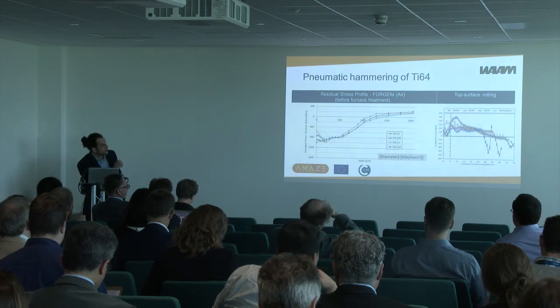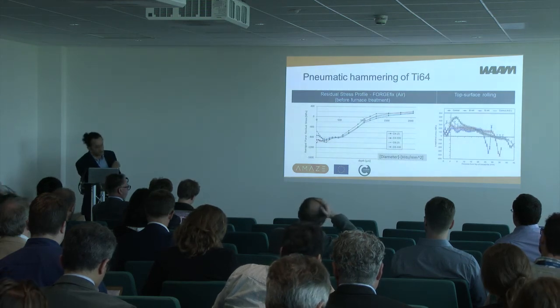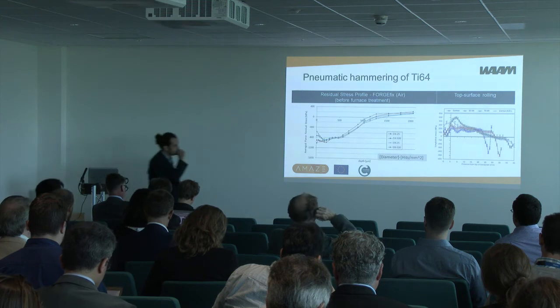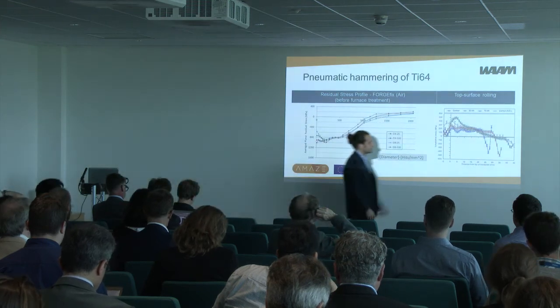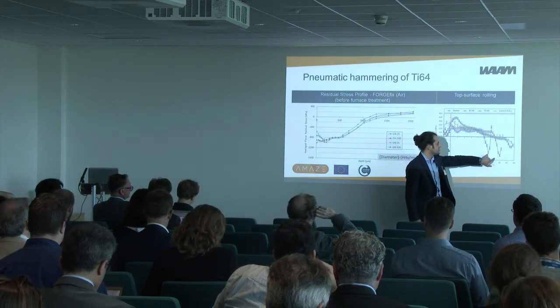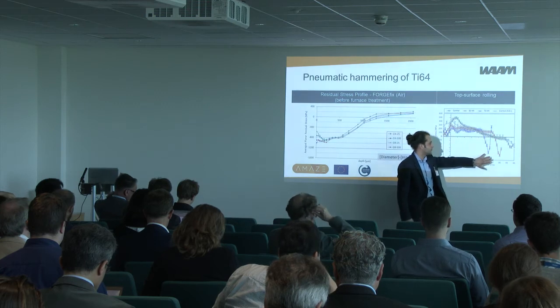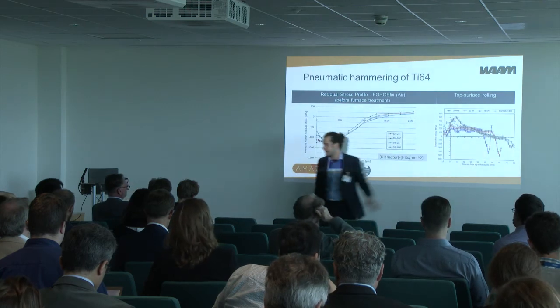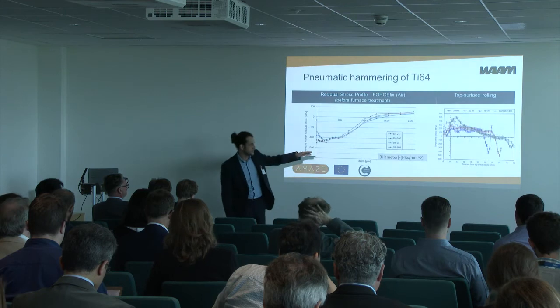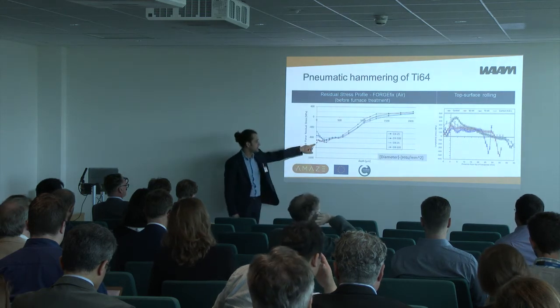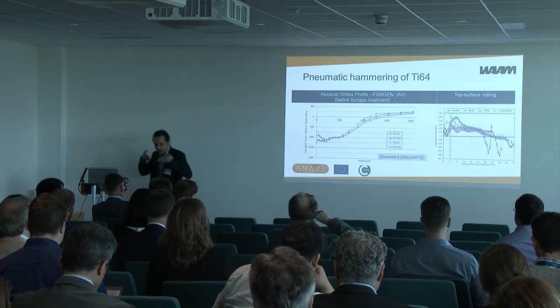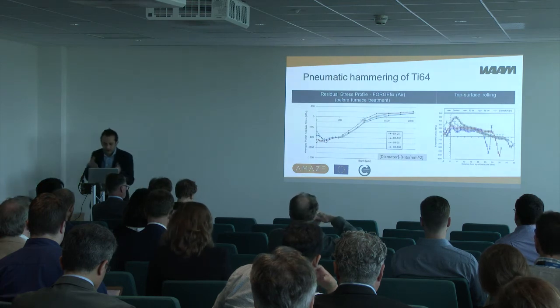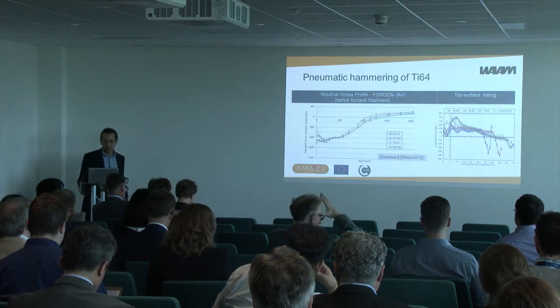And this is just to provide you a comparison with the case of the surface rolling. And you can see that indeed, these compressive stresses are those introduced by the last rolling step, which is not followed by an annealing step. And you can see they go as deep as 500 megapascal, while here we are much lower. And that's because the energy is much more concentrated in a smaller area.